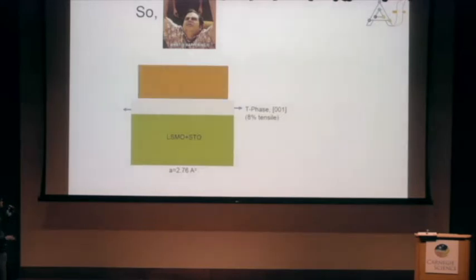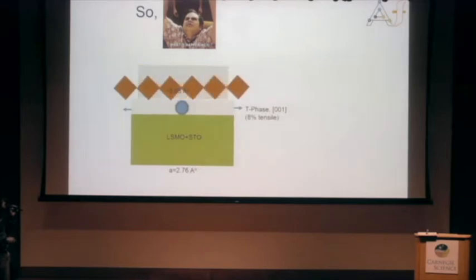So once there is strain relaxation, the incoming material should have a lesser in-plane parameter compared to this strained T phase. But there is a substrate constraint. So the way the system accommodates this is by rotating the crystals from 001 to 111. And when you rotate it, you still have a higher in-plane parameter. So what we need to do now is to apply some kind of compression.